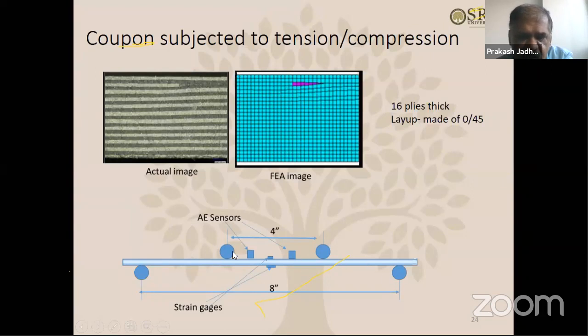If you subject the coupon to standard four-point bend boundary conditions, the coupon is going to bend like this. If you put strain gauges on the bottom surface and the top surface, then by mechanics you can tell that the bottom surface is under tension and the top surface is under compression. So by simple bending, you can achieve tension and compression in the coupon.